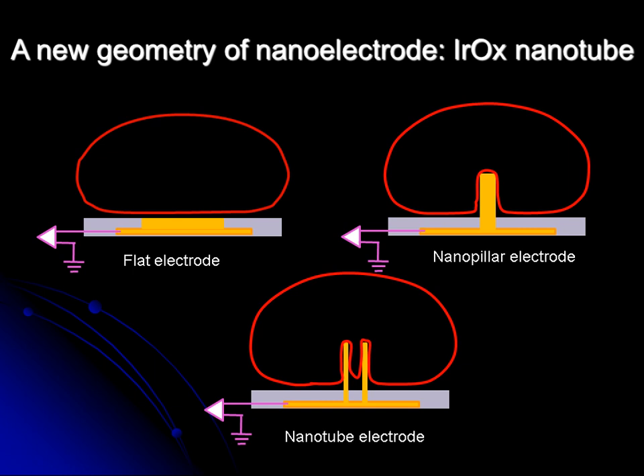Instead of the nanopillar electrode, which is vertical but solid, we made a nanotube electrode, which is vertical but has a hollow center. And the diagram is drawn on the bottom here. What you see is a cross section. It's actually a cylinder. It has two side walls, has a hollow center. When the cells are growing on top of the nanotube electrode, the cell membrane not only wraps around the outside, but also grows into the tube. That is what significantly changes the interaction between the cell membrane and the electrode.